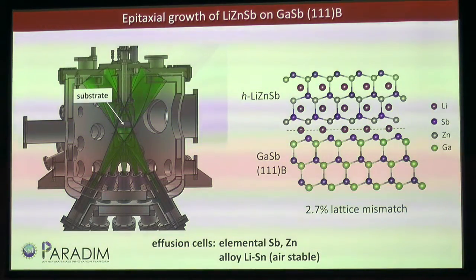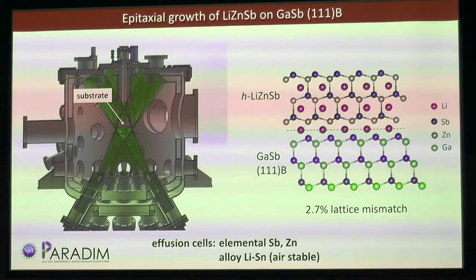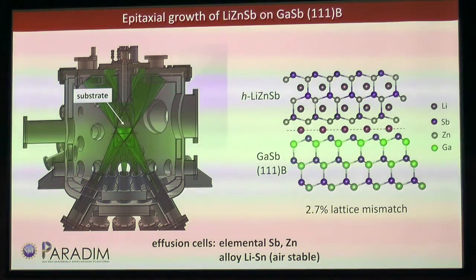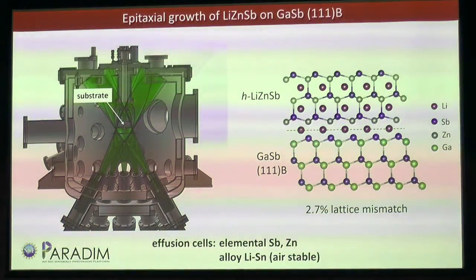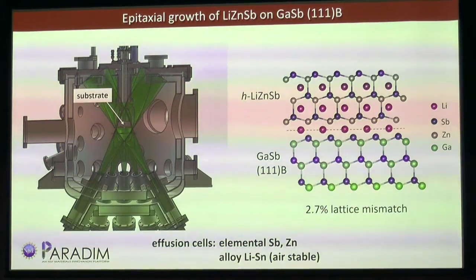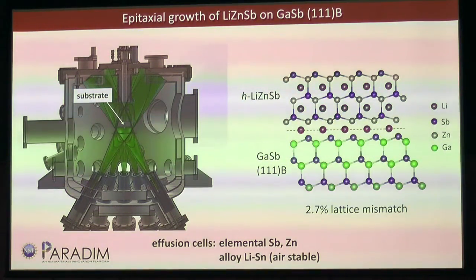We grow them in the PARADIM system. We use elemental metals for antimony and zinc, and we use an alloy for lithium and tin. The reason we do that is because the lithium-tin alloy is very air stable, or reasonably air stable, compared to lithium metal. And because the lithium vapor pressure is orders of magnitude higher than tin, we can reasonably evaporate just lithium. Okay, so we grow these by molecular beam epitaxy. We've chosen gallium antimonide 111 because it's a reasonable lattice mismatch, a little bit less than 3%.